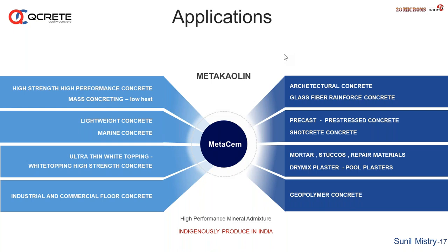We have to take all the care during the production of mass concreting. There are literatures available, and trials have been conducted using slag concrete and fly ash concrete, where sometimes strength is always an issue. If we add more low fast reactive mineral admixtures, you can add 1 or 2% of Metakaolin in combination with the fly ash and the slag, you can get the right properties, especially compressive strength and durability aspect, and can control the heat of hydration also.